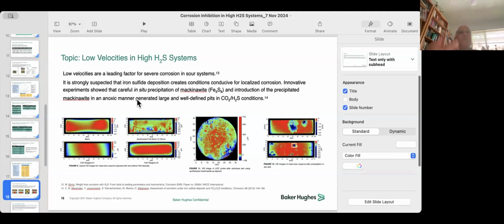It was hard to reproduce and to get test methods of recreating corrosion. One of the ways we did it is in anoxic environments, and you have to be very careful. You want your facility completely oxygen free, at very low amounts of oxygen. You then create mackinawite, and when you introduce it, these are interferometer images. So you can see this is a case where it's nice and smooth. But you see tremendous pitting. These pits appeared when we introduced precipitated mackinawite. And by doing that, you see the problems.